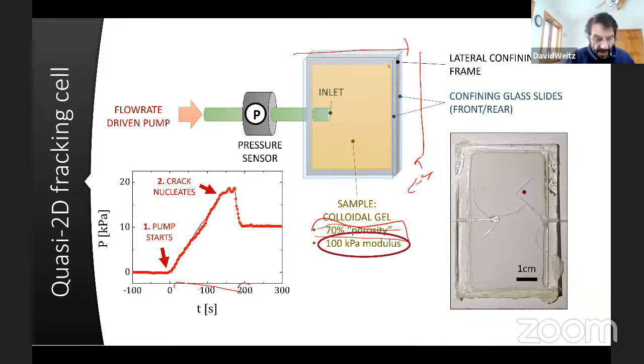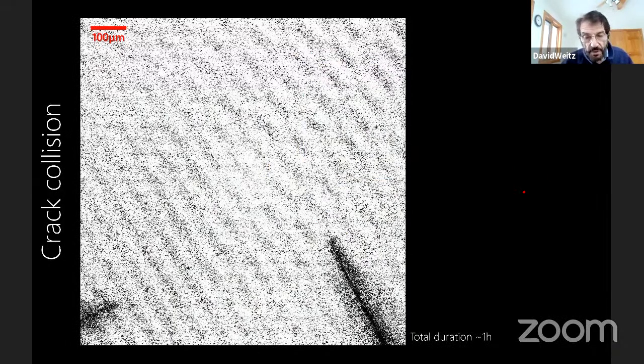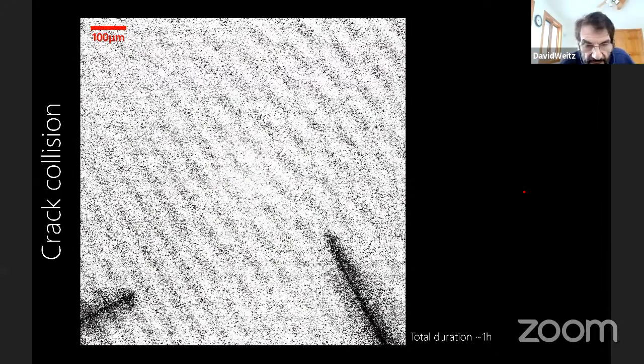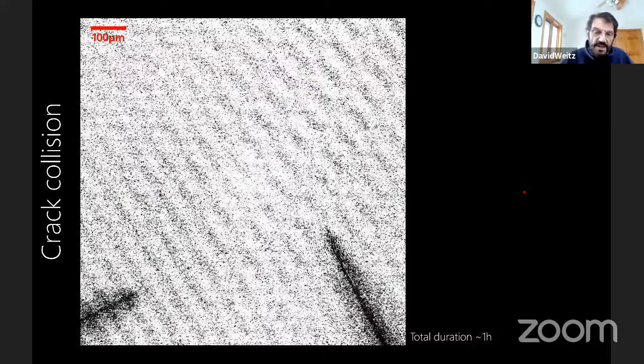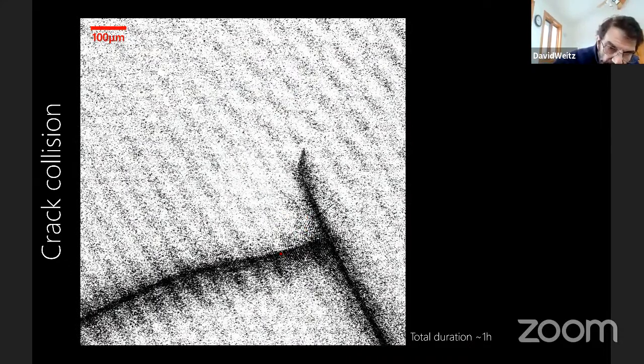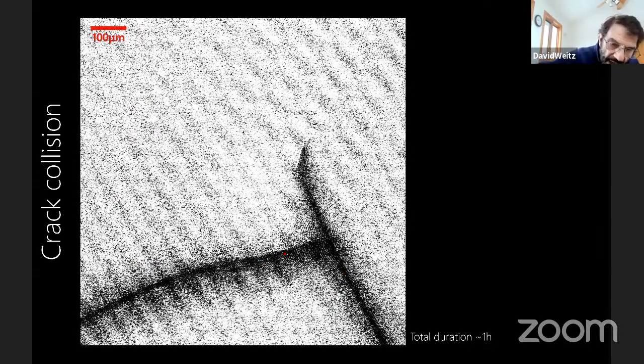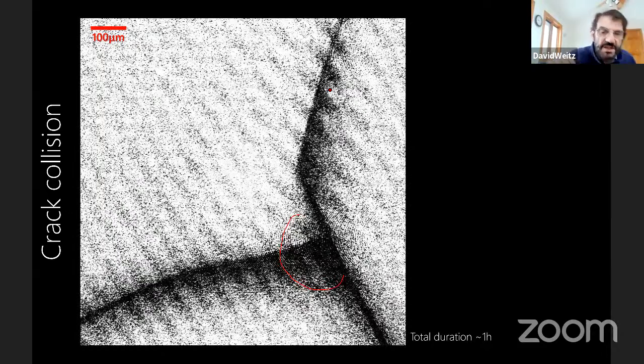Here's an example of that, just to show you all the cool things that happen. We're injecting fluid. This is the crack moving from left to right. There's another crack moving, and you see how the two cracks interact. You see that this crack, let me see if I can write on this movie, this crack has run into the other crack, but the other crack has moved in this direction, it's changed directions. That's not a random event, that's driven by the interaction between the cracks.